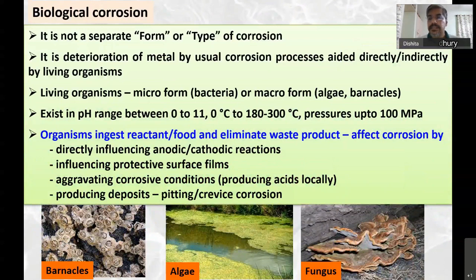Biological corrosion is not a separate form of corrosion. It's mainly due to bioactivity on the material, like barnacles sticking onto the surface, presence of algae, presence of fungus on the metal surface. They affect corrosion by directly influencing anodic and cathodic reactions. It can enhance one of the reaction rates. If the cathodic reaction rate is enhanced, the anodic reaction will automatically get enhanced.